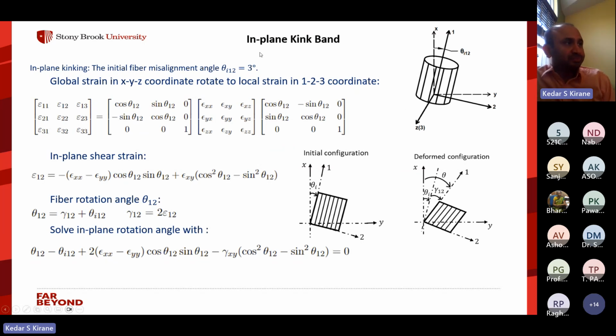So imagine that, let's say, the kink band is developing in plane. Okay, so we can imagine that the overall loading is along the x direction, and then one direction is the fiber direction. There is usually an initial misalignment angle theta I. So any local shear will add to the theta and will end up involving more rotation. This rotation will further increase the shear and it will keep accumulating. So this is what leads to the shear localization. So in our model, we basically calculate this rotation and calculate this shear.